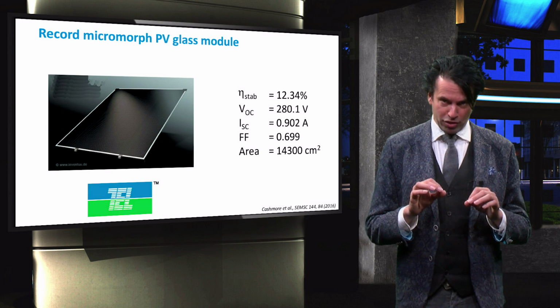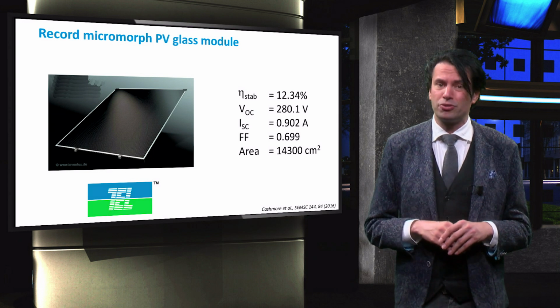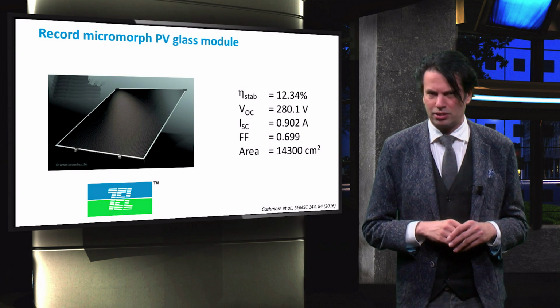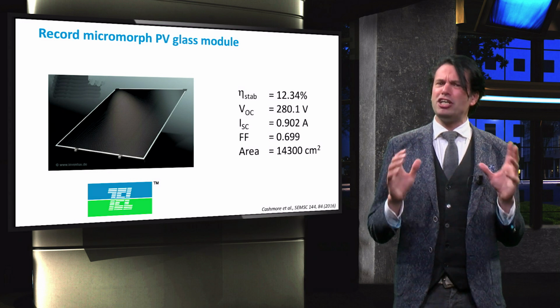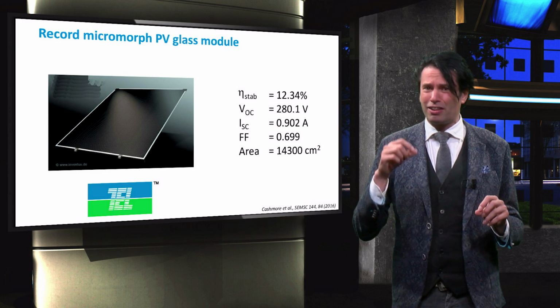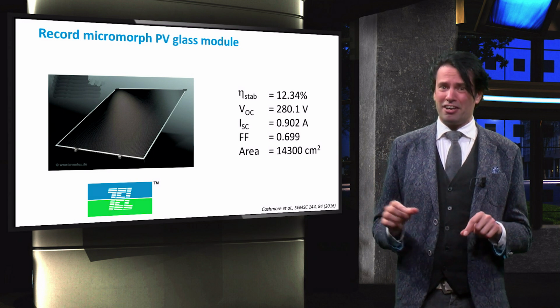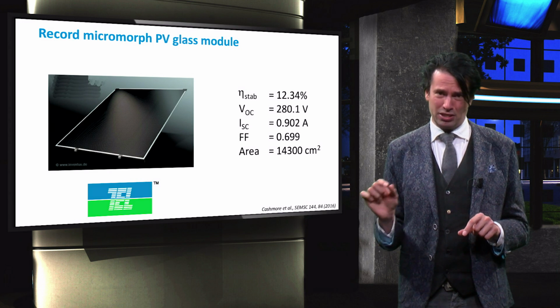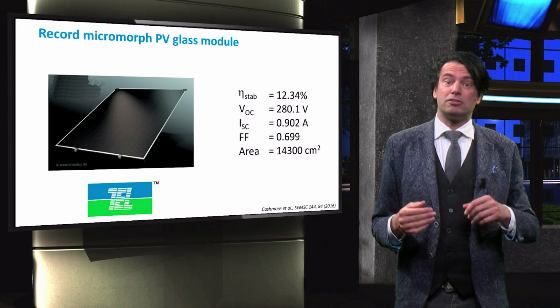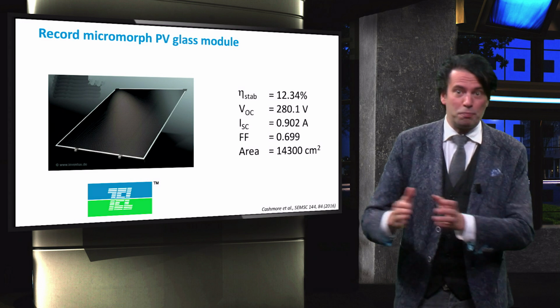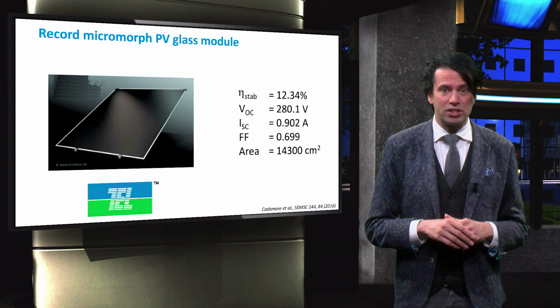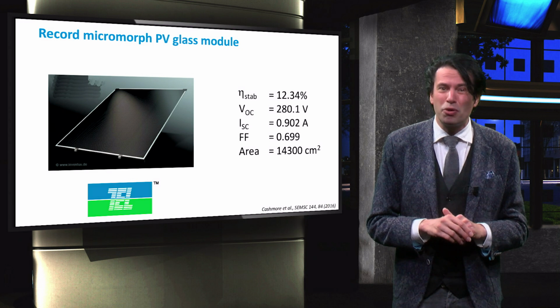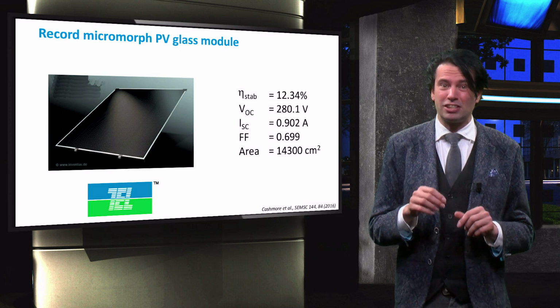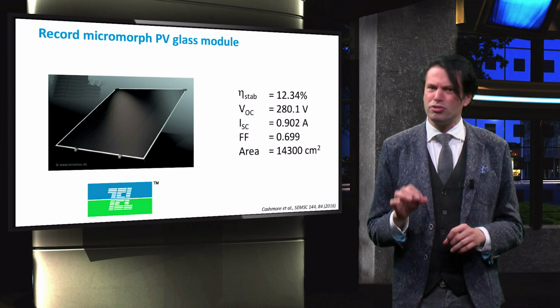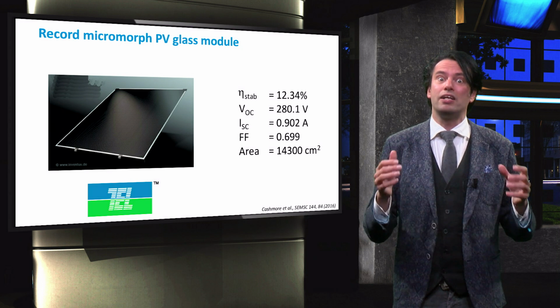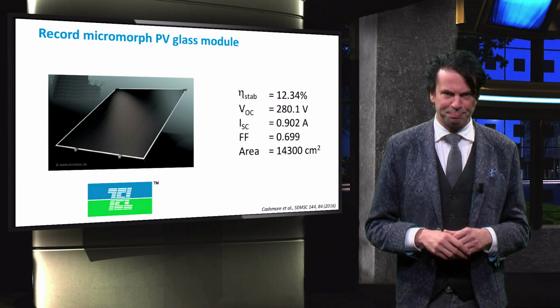The record module conversion efficiency obtained by Tokyo Electron is 12.34%. This is an impressive achievement as you consider that 12.63% is the record for a device area of only 1 square centimeter. Upscaling the micromorph technology from 1 square centimeter up to 14,300 square centimeters, only 0.29% in efficiency is lost. This shows that thin film silicon processing is a highly mature processing technology.